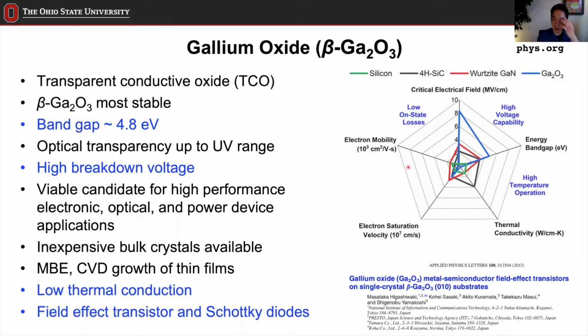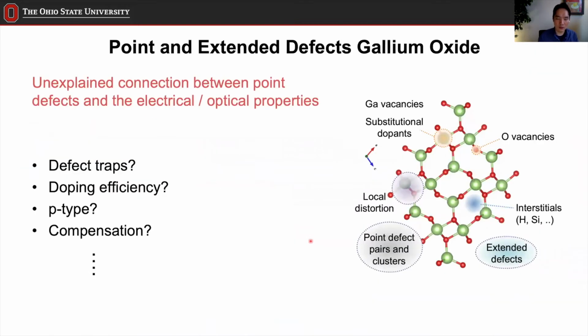Some examples of how we handle those include making an alloy of gallium oxide and aluminum oxide, for example. Then there's a way to handle the electron mobility issue. And thermal conductivity may become just a design issue, how we design exactly the device and the interface. Okay. So it's a pretty good candidate for the wide bandgap application. The device people that we work with try to make this gallium oxide device work.